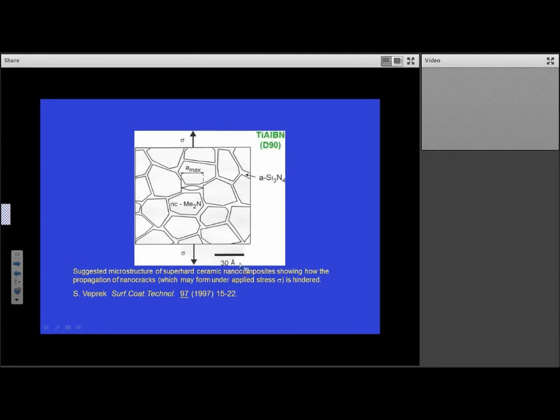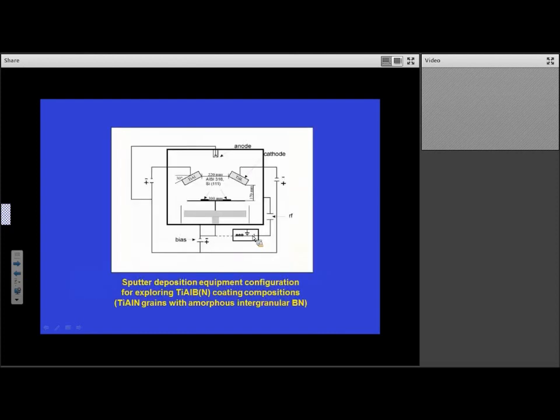We kind of moved from that and looked at titanium aluminium with nitrogen additions in an amorphous boron nitride matrix in order to get hard but yet relatively elastic nanocomposite coatings. And it's good that we can use sputter deposition techniques and electron beam techniques to do, in a way, combinatorial studies on the effects of different compositions of these materials. And in a single run, you can get a variety of compositions and look at the behavior of those different compositions in nanocomposite coatings.